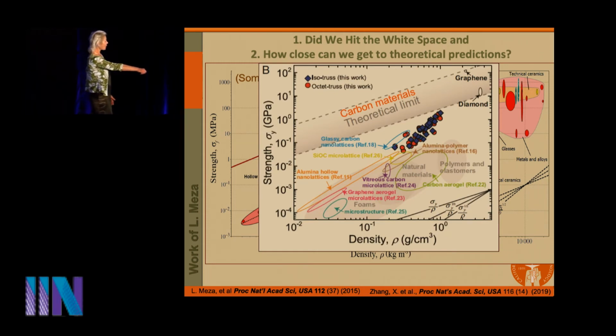So here's an example of carbon that we just published very recently. You can see that at higher densities, the carbon actually does in fact approach the theoretical limit. We also had to revisit this theoretical limit. What exactly is the theoretical limit when you're talking about materials that are practically all surface? And those of you who work on 2D materials certainly know that effect very well.